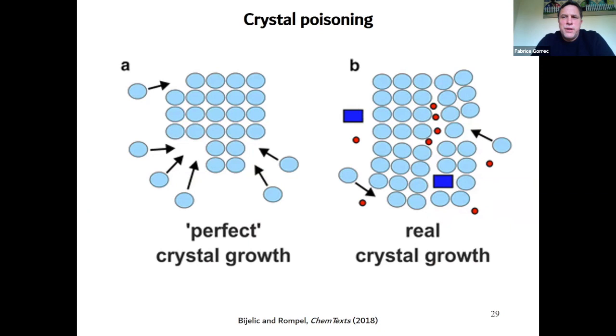I'm taking the opportunity to say that this is one good reason as well to screen smaller crystals. Bigger is not always better. Things can only get worse with growth. Obviously, the size of the crystal is important because the volume of the crystal that is shot, the intensity of the diffraction spots are directly proportional to the volume of the crystals that you have. But the structure of the crystal itself doesn't get better with growth unless you really, really super optimized everything, which I hope you do. But just don't forget to screen also smaller crystals, not only the big ones. It may also make a difference for the other parameters like cryoprotections, but that's another story.